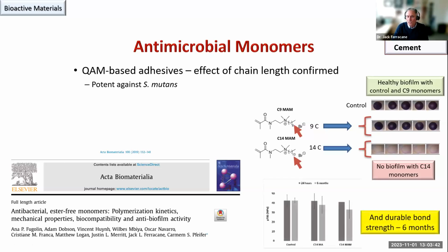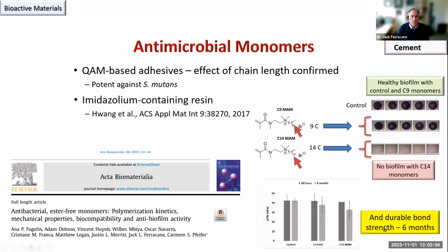Now, I want to put this into an adhesive material. Showed here's the control situation. Here's the 14 carbon chain monomer after 24 hours and after 6 months. And although there is some decline, it wasn't significant. So in general, we have durable bond strength even after 6 months.